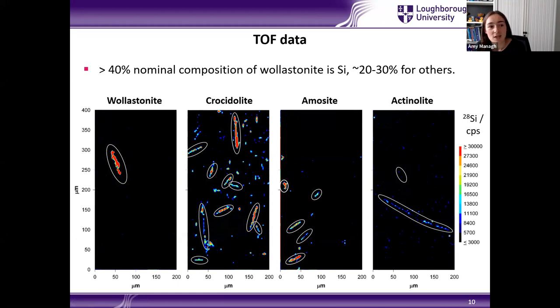There's a high proportion of silicon within the wollastonite fibers. Over 40% of its nominal composition is silicon. So we can see a very strong signal in our wollastonite fiber here. It's also present in the other three fiber types as well, though. So you can see everywhere where there's a fiber, we see a strong silicon signal. Silicon is not necessarily that good then at distinguishing between the different fiber types.